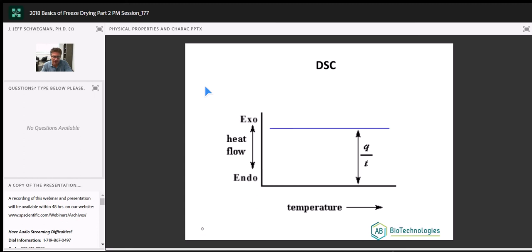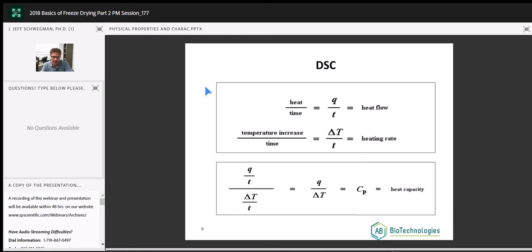And basically, change in temperature, increase in temperature, we control the heating rate, that's what we program in. The heat flow is the amount of energy that's put in to keep the pans at the same temperature. Now the beauty of this, we monitor the heat flow, we program in the heating rate. If we divide the heat flow by the heating rate, we can now extract out some of the thermodynamic variables we might be interested in, starting with the heat capacity. Now heat capacity, the definition is the amount of energy required to raise the temperature of 1 gram of a species 1 degree Celsius. It takes a different amount of energy to do that for different materials, okay? So each different material has a different heat capacity.